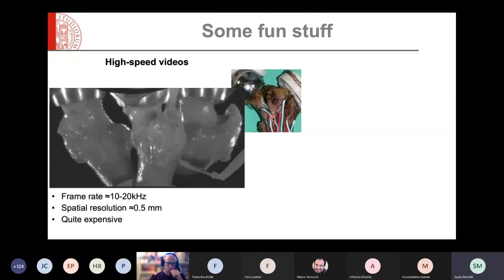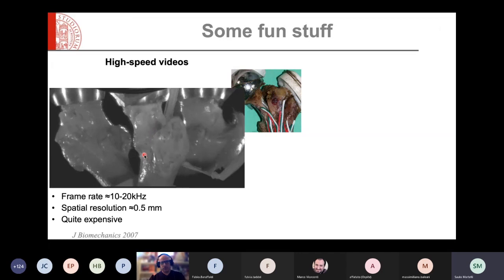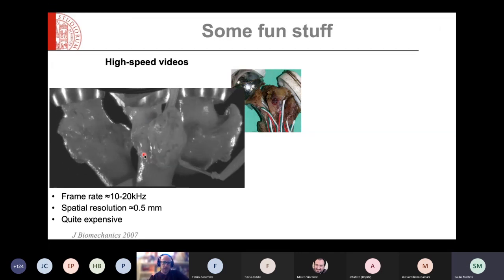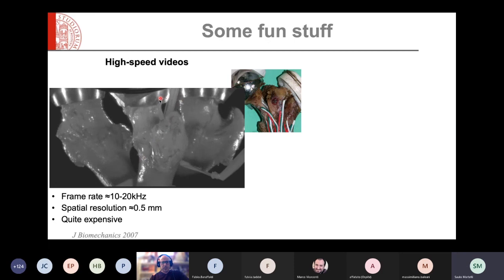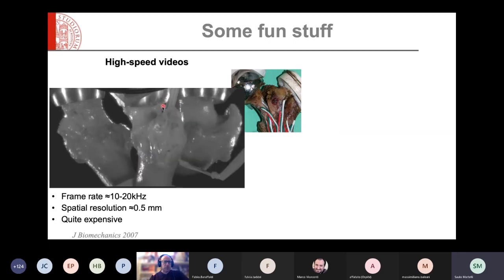Now, the fun part of our work is also to break bones. This is the cathartic part of our experiment. So this is a broken femur. When you see a broken femur, you don't know where the fracture started. You just see how it is broken. So we started using high-speed videos to acquire the fracture event and to observe how fracture starts and propagates with high-speed cameras, which could acquire images between 10 and 20,000 frames per second. This was very nice. We were the first to do this on the femur.